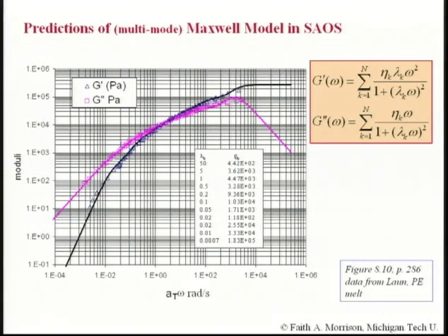Also, at the high frequency end, the data only fit as long as you pick a relaxation time that's similar to 1 over where there is actually data. So for instance, the data here stop at about 10 to the third. So 1 over 10 to the third is the longest relaxation time that we can report. I mean, excuse me, the shortest relaxation time we can report.